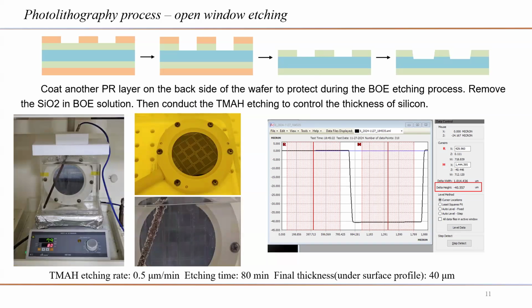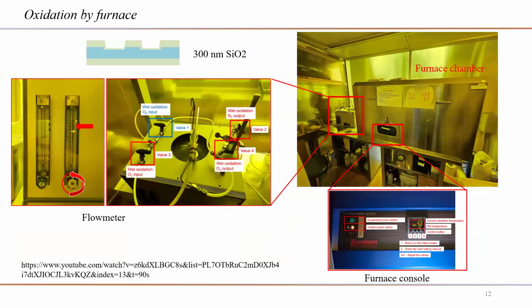The TMAH etching rate is 0.5 micrometers per minute. Our desired thickness was 40 micrometers, so we set the etching time as 80 minutes, and finally we got a thickness of 40.557 micrometers. Next, we do the second oxidation process to make a 300 nanometer silicon dioxide layer.